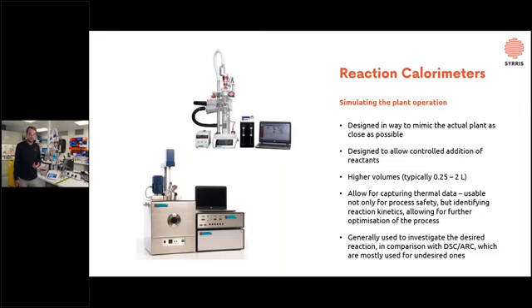They will usually have higher volumes compared to the screening methods, the DSC or the adiabatic calorimeters, usually from 250 milliliters up to 2 liters. They have provisions for capturing the thermal data. So if you think about it, it's not only usable for safety studies, but we can find the kinetics and different reaction paths, and it will allow us to further optimize the process to run as efficiently as possible. And reaction calorimeters are generally used to investigate a desired reaction, so the process we actually want to follow, which will create our product, in comparison with the microcalorimeters or adiabatic ones, which are mostly used for undesired reactions or just screening studies. So those are the main types of calorimeters.